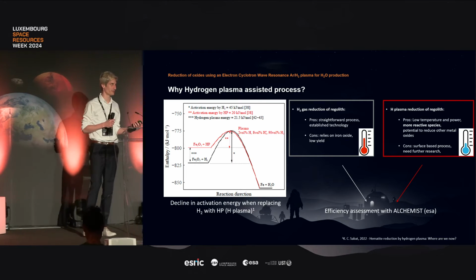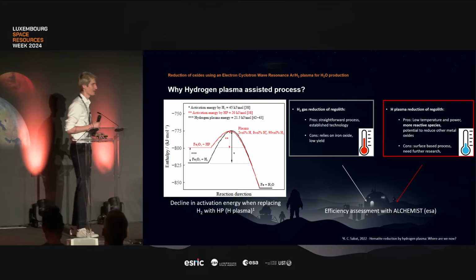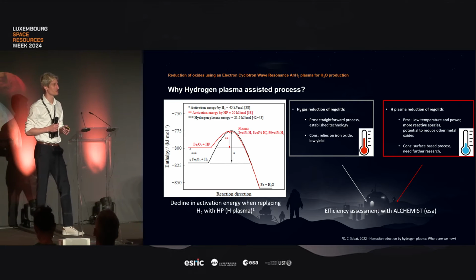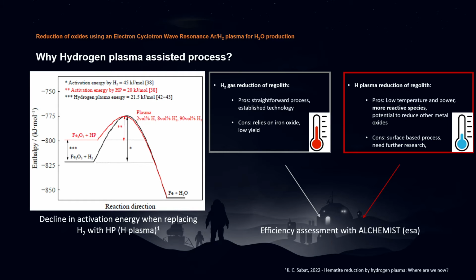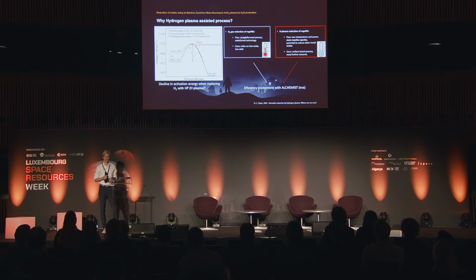Well, when we look at the graph on the left, we can see the activation energy requirement, like a small barrier, and we have the black line and the red line. The black line represents the hydrogen reduction process with the gas, and we see that we need to cross that mountain to get to the metal and water, to our products. But if we use plasma, hydrogen plasma, we see that mountain becomes much easier to pass.